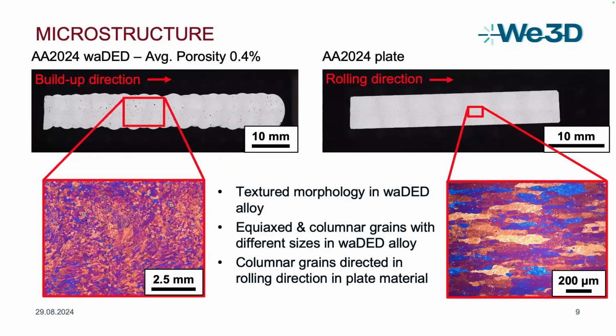Here we have an overview of the final microstructures. On the left side, again, the wire arc DED material with an average porosity of 0.4%. And here we have the Barker etched conditions of this material. We can see that we have kind of a wild microstructure. We have equiaxed grains, we have elongated grains with different directions also because of the process strategy. So very inhomogeneous. And on the right side, we have the microstructure of the rolled material, which is directed into the rolling direction as we would expect from a plate material.